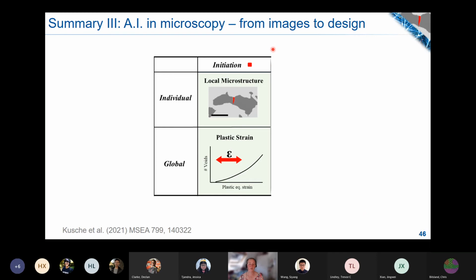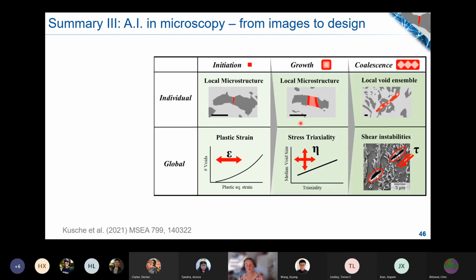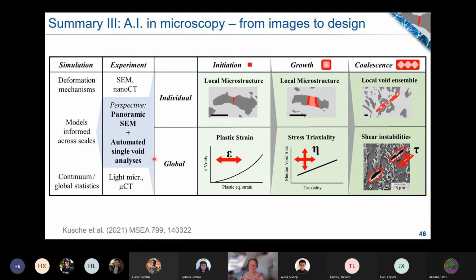So to put this together, what we've been trying to do with this approach is to really combine the local scale of initiation and also growth and coalescence of damage sites, depending on the local microstructure, and compare that with a global view in terms of how, for example, nucleation of damage depends on something like the plastic strain. We've looked at that also in terms of growth. So we've also changed triaxiality, looking at different notch samples. We've also done biaxial tests. And you can do all of these with essentially the same trained networks, all the way up to coalescence, looking at how the different damage sites will coalesce into instabilities that will lead to failure, because the maps are big. And I think it's actually quite nice because we can now have this method.